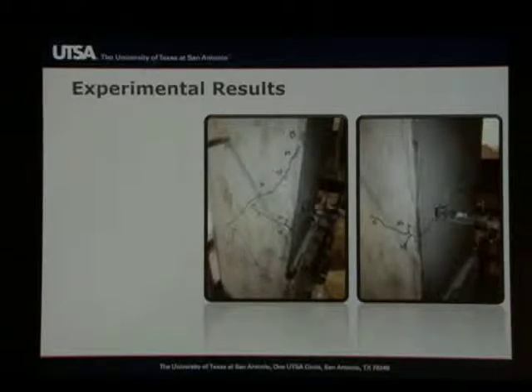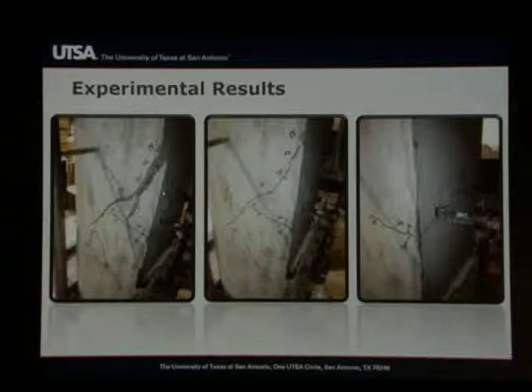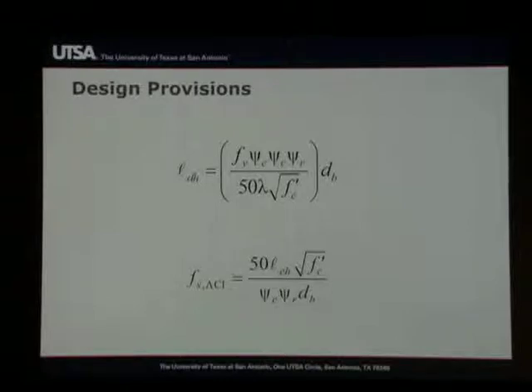And there is that tendency to grow towards the back of the hook, and then we start to see those cracks evolve. The failure surface starts to look like a cone, and then finally you get pull-out of that big chunk of concrete, sometimes accompanied by side blowout in the specimen. So if you read literature on hooks, you will see people describing side blowout failures. They do happen, and they did happen in our study, but in most of those instances, it's hard for us to call it a side blowout failure by itself. It's more like a secondary type of failure. Okay, so on to the design provisions.